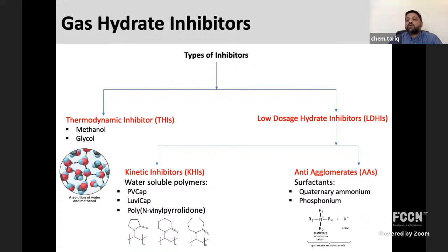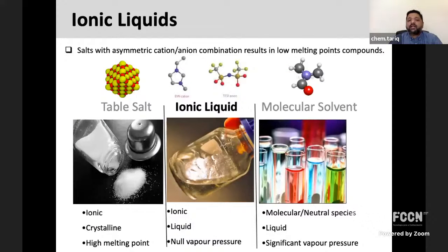The other type of LDHIs are known as anti-agglomerates. These are generally surfactants, quaternary ammonium or phosphonium. They allow the formation, but they do not allow the hydrates to stick together to form bigger chunks and clog the pipeline. That's why ionic liquids came into existence, because we know ionic liquids are designer solvents made up of different combinations of cation and anion, which can result in low melting point salts compared to conventional salts, and they can have the properties of both salt and molecular solvents. So these are the obvious choice to use as hydrate inhibitors.